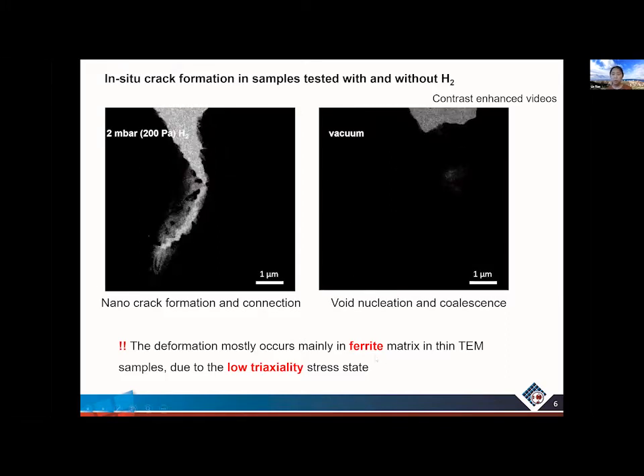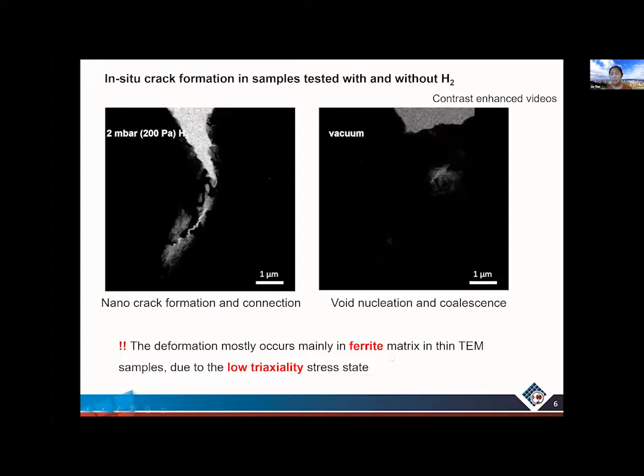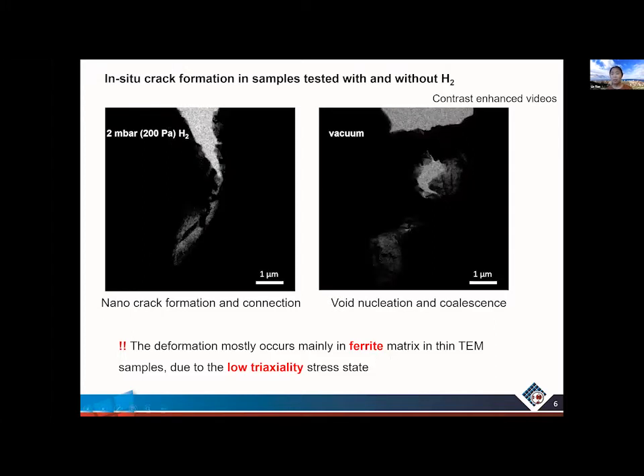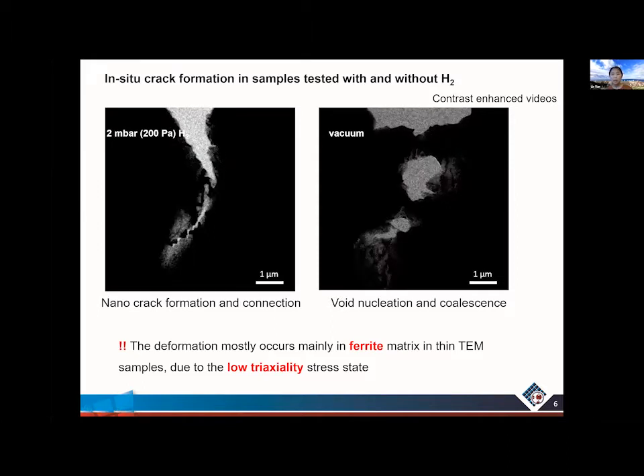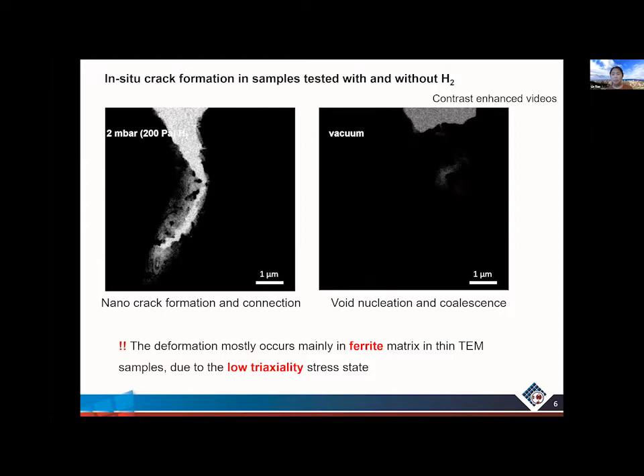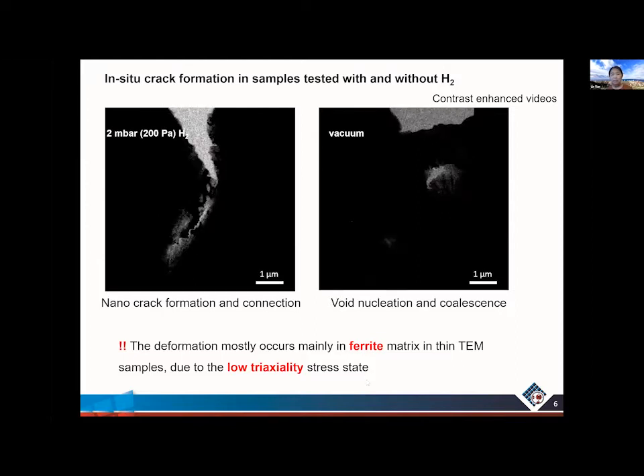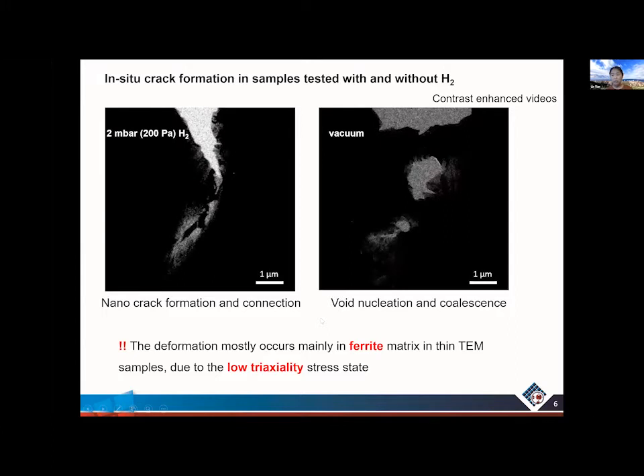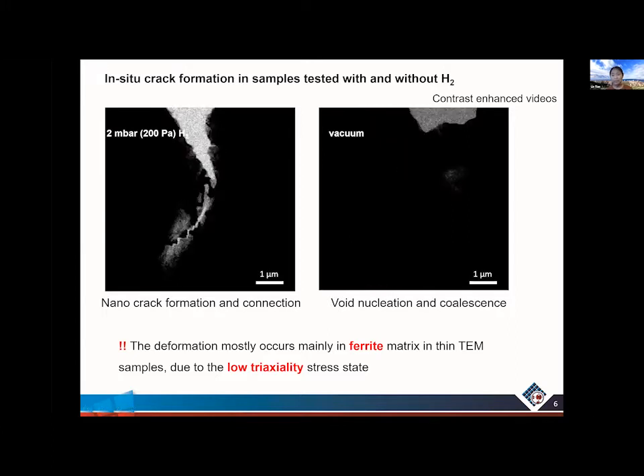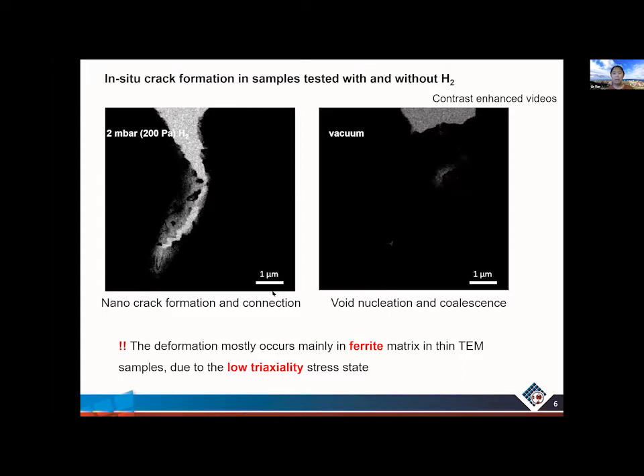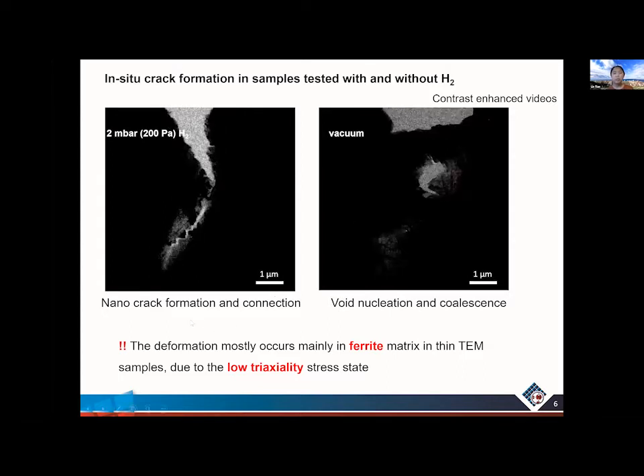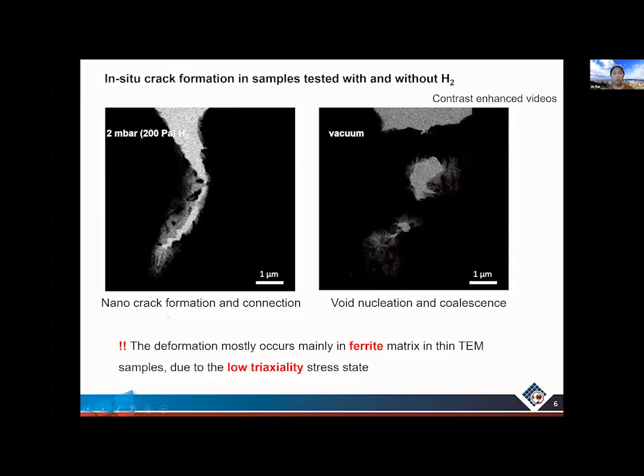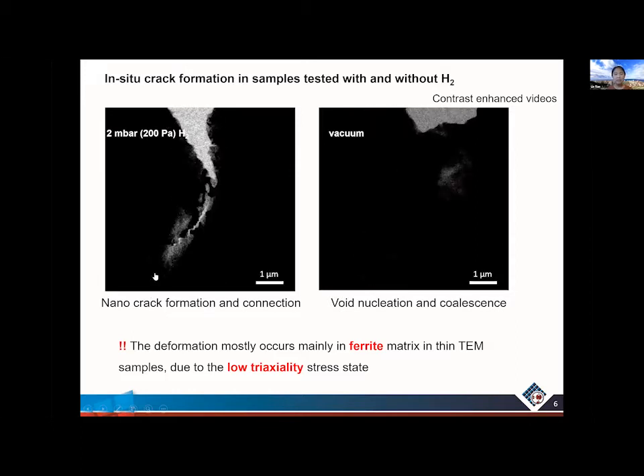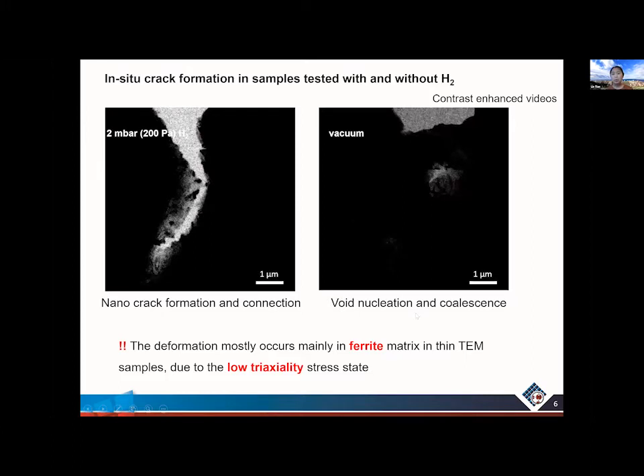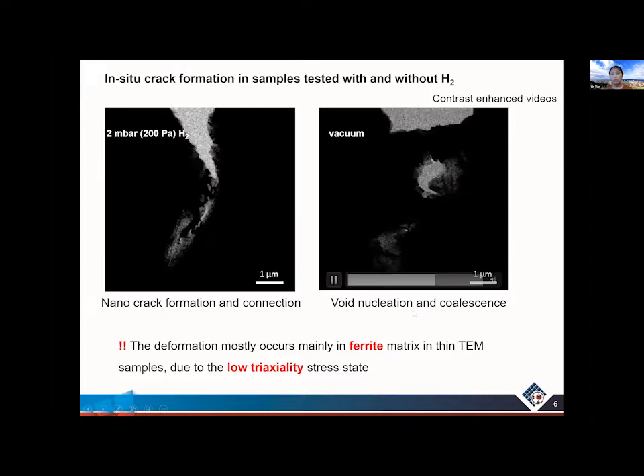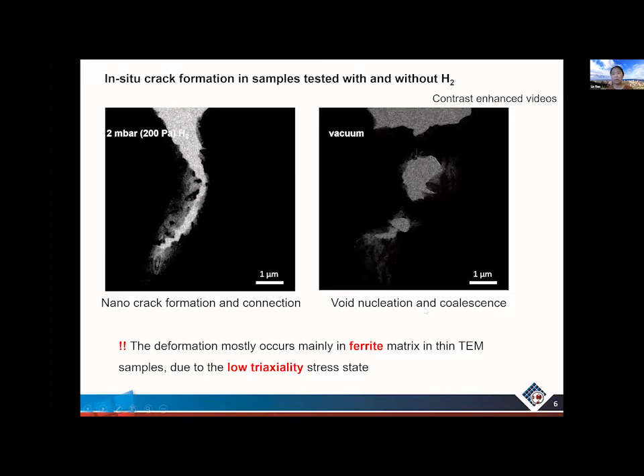This is due to the reason that the TEM sample is really very thin and it's in a low triaxiality stress state. However, with the same low triaxiality stress state, we still see this hydrogen-induced very distinct, very different deformation behavior here. With hydrogen gas, we see nano cracks form and then connect and propagate. But without hydrogen, just in vacuum, we see void nucleation and then coalescence.